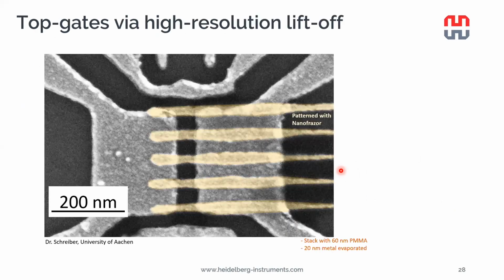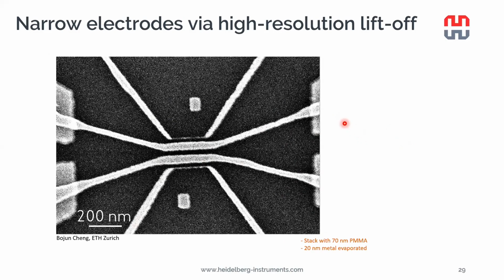So I want to show quickly a couple of examples made by the high resolution liftoff process. First of all, here we have a device that was first fabricated by electron beam lithography, these gray electrodes. And then we overlaid and patterned these very narrow top gate electrodes on top using the NanoFrazor. And there's a very thin alumina oxide dielectric in between. Another example, which is also a mix and match with electron beam lithography and NanoFrazor. These pads here were defined with electron beam lithography, and these very narrow electrodes were overlaid on top with the NanoFrazor. These are only in the range of 10-20 nanometers wide lines, however, they are electrically conductive as verified by electrical measurement.